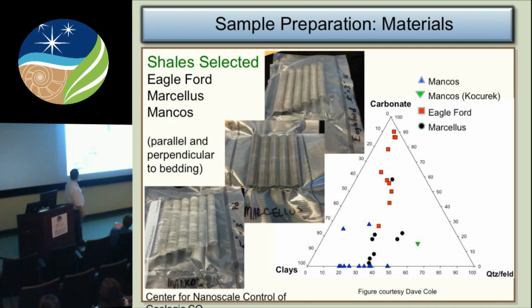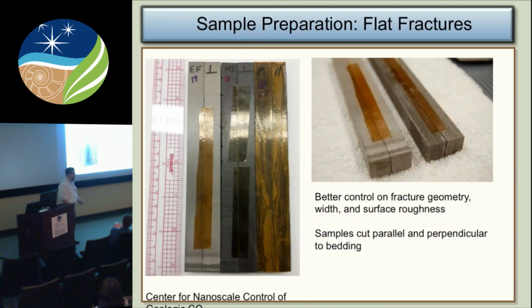We started worrying about fracture uptake in shales because of its effects on CO2 sequestration. Oftentimes shales are envisioned as cap rocks in these kinds of environments where the sandstone below it is expected to be where the CO2 might be stored, often with a brine solution that will react. The question is, how good are those shales as real cap rocks? So we've been looking at uptake in 3: the Mancos Shale, the Marcellus Shale, and the Eagleford Shale. This gives you at least some idea. These things are very variable in their compositions, but in general you can describe them as a mix of carbonates, clays, and a quartz feldspar mixture. The Eagleford here is, you can see, a very carbonate-rich shale. Mancos rather carbonate poor.